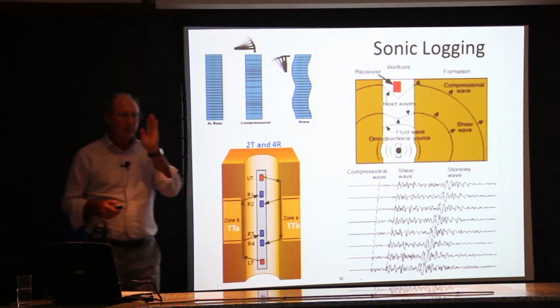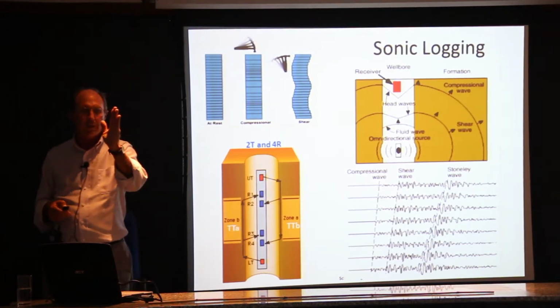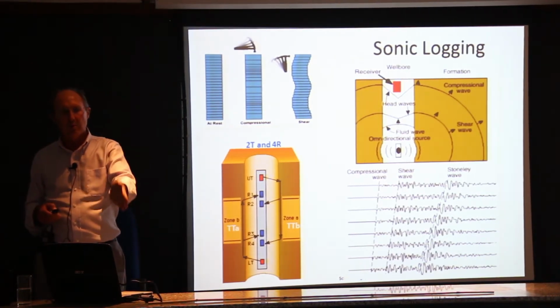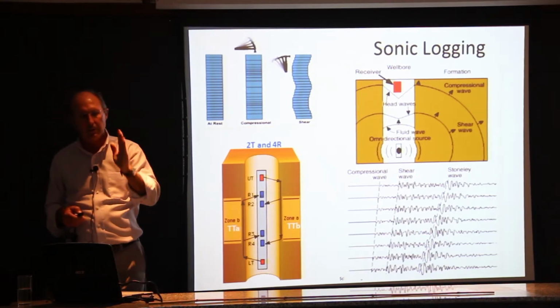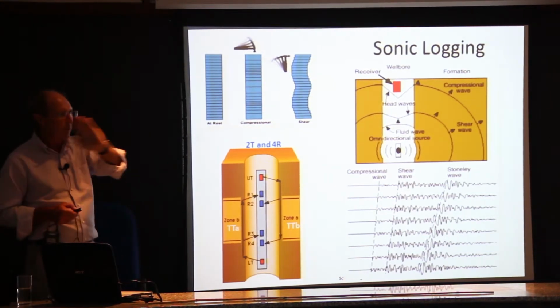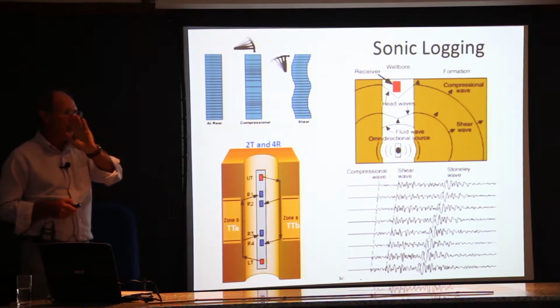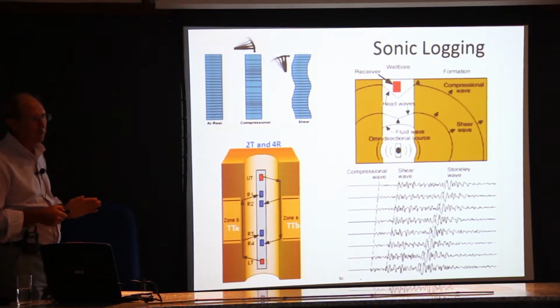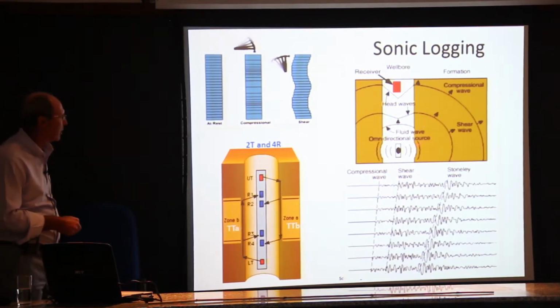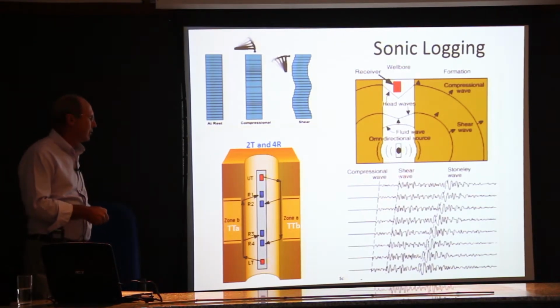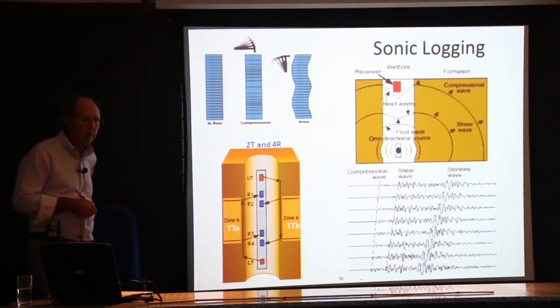If a shear wave hits a fracture, it will split into two. One shear wave will go parallel to the fracture, that's the fast shear wave. You'll have another shear wave that's propagating 90 degrees to the fracture strike. That's the slow shear wave. So we look for shear wave anisotropy as an indication of fractures.